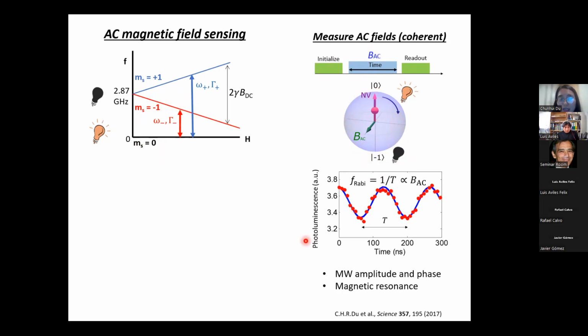So in this case, if we monitor the photoluminescence as a function of the duration of the microwave field, we can see that it will follow the Rabi oscillation, which is because NV spin is rotating between 0 and -1 state periodically. And from the frequency of the Rabi oscillation, we can measure the local microwave field at the NV location. So this allows us to measure the amplitude and phase of microwave fields, and also study the magnetic resonance or ferromagnetic resonance of the quantum material.